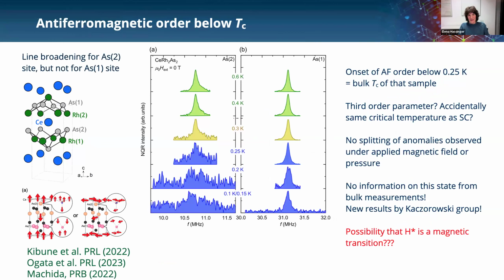Okay. And to make the situation even a bit more complicated, there's also evidence for an antiferromagnetic order, but this occurs at lower temperatures, roughly at Tc. And this evidence comes from NQR and NMR, where they see a broadening of one of the arsenic lines. And this broadening sets in roughly at the bulk Tc of that sample.